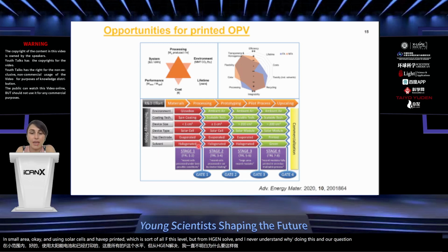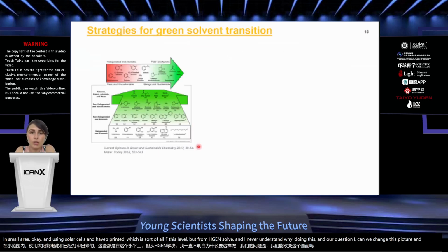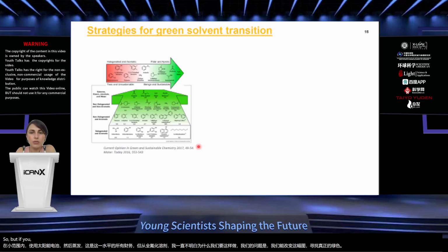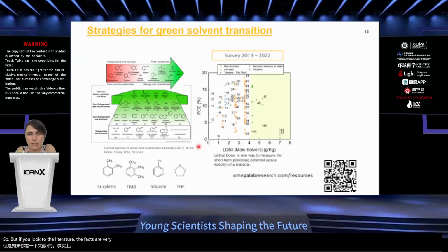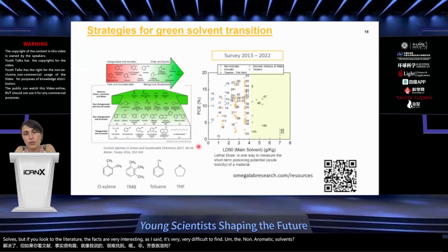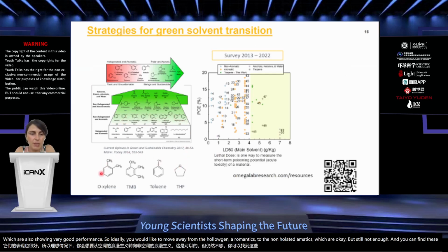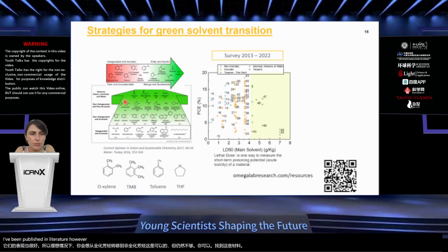And our question was, can we change this picture and look for really green solvents? But if you look at the literature, the facts are very interesting. As I said, it's very, very difficult to find non-aromatic solvents which are also showing very good performances. So ideally, you would like to move away from the halogenated aromatics to the non-halogenated aromatics, which are okay, but still not enough. And you can find these materials have been published in the literature. However, if you want to move to non-halogenated, non-aromatic, or even ketones, esters, then you are much more limited.